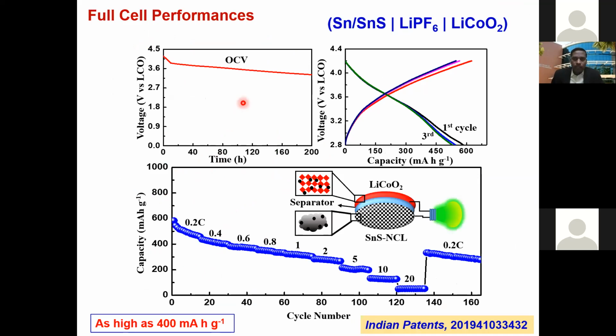Since the tin sulfide could work much better as an alternative anode for lithium-ion battery, we went for the full cell. This is a typical commercial level lithium-ion battery consisting of not graphite but tin sulfide as an anode, and the conventional lithium cobalt oxide as a cathode, and lithium hexafluorophosphate as an electrolyte. And OCV is stable for 200 hours, and you get a flat voltage plateau very nearly similar to what we get for the commercial lithium-ion battery. And what is important is the discharge capacity.